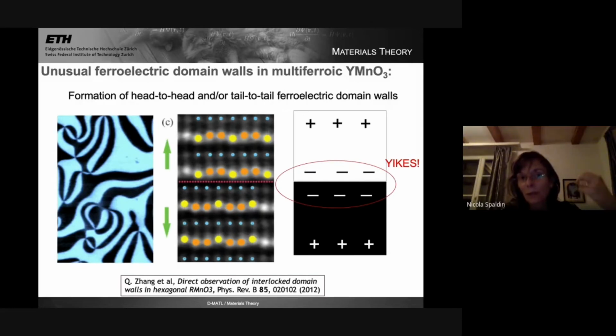Because of the unusual mechanism in this multiferroic yttrium manganite, these kind of domains get trapped in the structure and they can't get out. So the material's stuck with these head-to-head and tail-to-tail dipoles, which make it very unhappy. The way that it responds to that is by bringing charge in here to screen this diverging electrostatic potential. So in this case, when two negative charges are pointing towards each other, it has to bring in some positive charge to cancel them out.